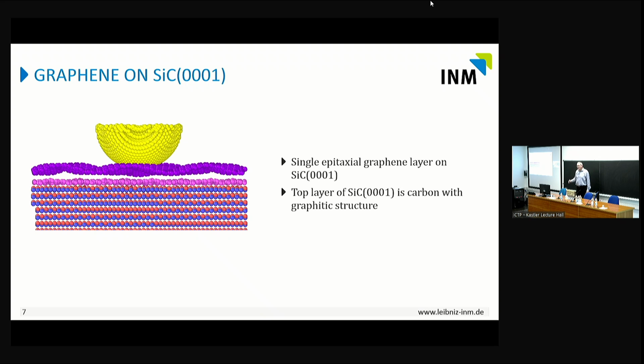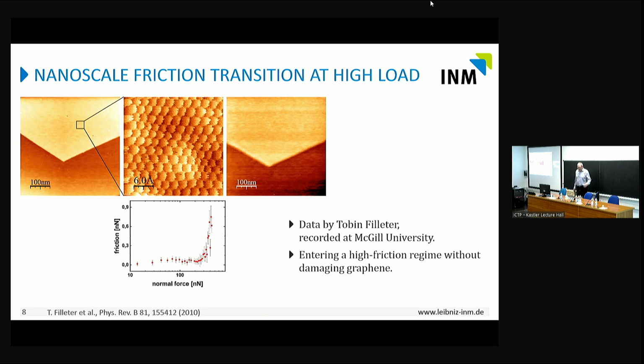And we got interested in friction on this layer. There's a paper by Tobin Filleter a long time ago where he shows that two layers have different friction than one layer, but that's not what I'm interested in here. What we always found is that at a certain threshold load, suddenly the friction goes up. And that was at different loads, but it's always there.